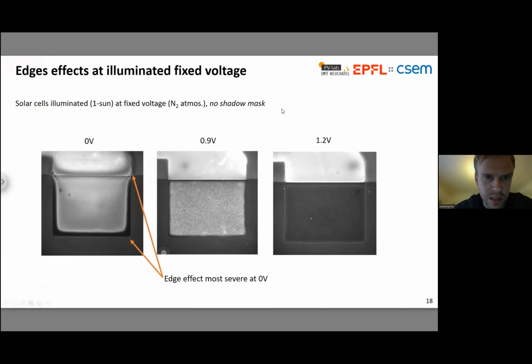And I did so in a series of experiments where I put cells in our stability tester, and I held them at fixed voltage. So rather than doing MPP, holding cells at fixed voltage, and I picked three voltages, 0, 0.9, and 1.2. So we've got a short circuit condition, kind of moderate forward bias at 0.9, and then a forward bias condition where we expect to be very close or perhaps above the built-in voltage at 1.2. And indeed, we see exactly that: it's the short circuited cell that has the most severe effects happening around its edges. So that seems to be fairly good evidence in favor of this ionic hypothesis.